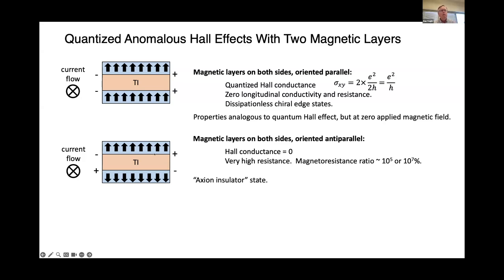You can also arrange it so the magnetizations on the 2 layers are anti-parallel. In that case, the quantum Hall conductivities on the two surfaces are of opposite signs, so they'll cancel. You'll get a Hall conductivity of 0 and end up with very high resistance. And that's called the axion insulator state. So all these states have been seen, as I said, with magnetically doped topological insulators, but generally at quite low temperatures.